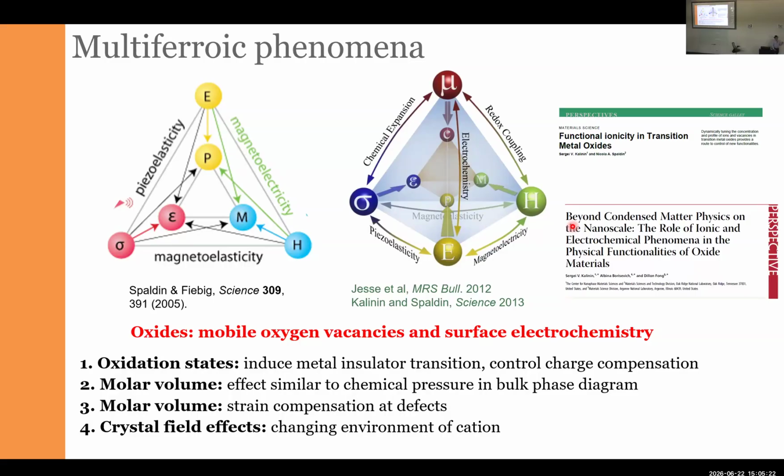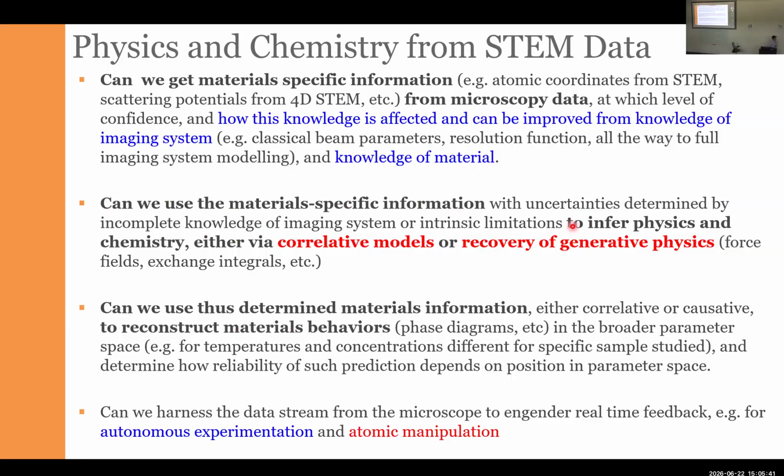Well, the great thing is that if we can measure 1 part out of 100 or 1 part out of 200 for the atomic spacing, we can basically use this chemical strain measured directly on the atomic level as the measure of the concentration of vacancies inside the materials. It's actually super cool. This being said, nothing is for free.